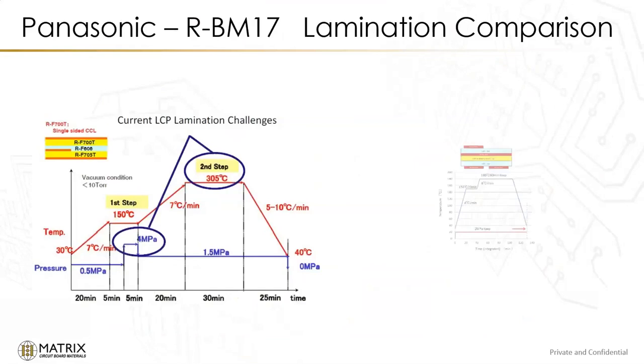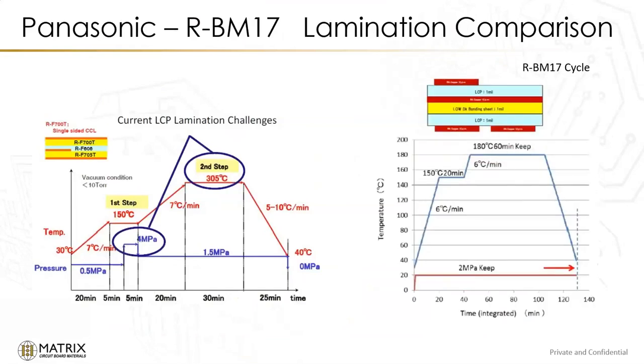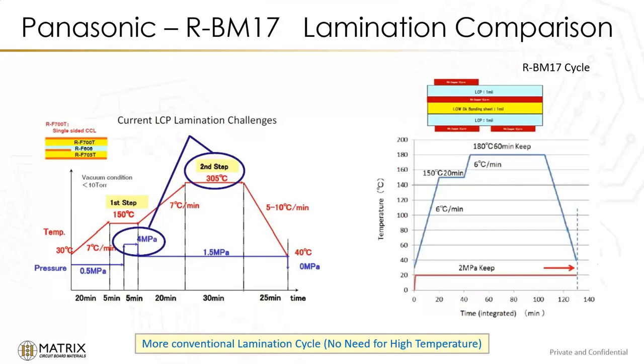So with the RBM 17, this is more of a conventional type cycle that would be used on other type products where we've got one constant pressure and we've got heat ramp that goes up to 150 C and then on up to the cure temperature of 180 C, which is not anywhere near the 305. And it's very close to what is being used today for many products conventionally being laminated. So the RBM 17 is a good option in that case. So more conventional lamination cycle.